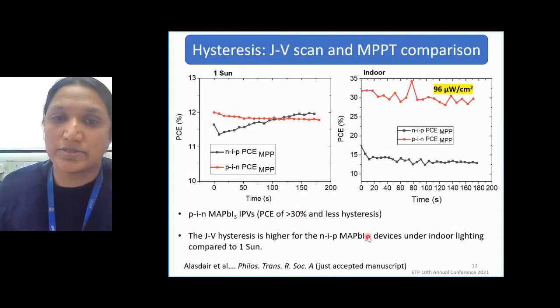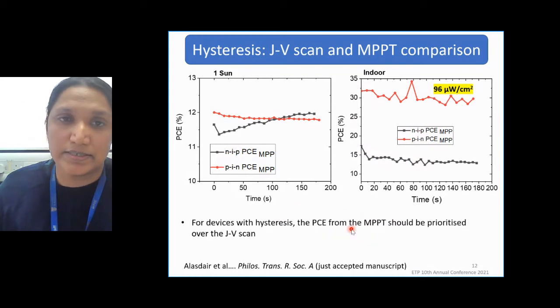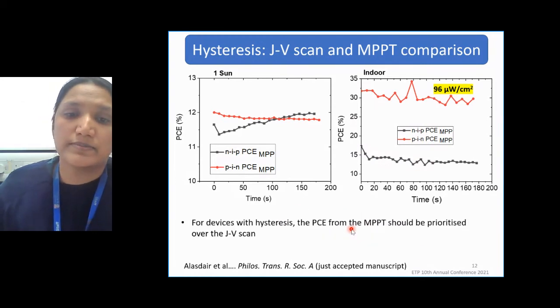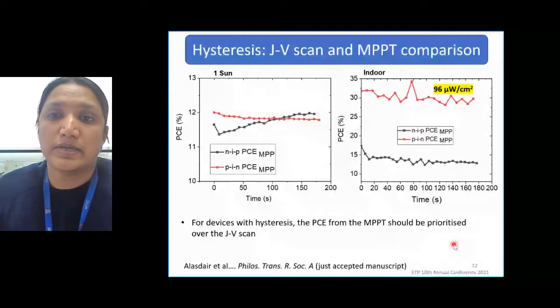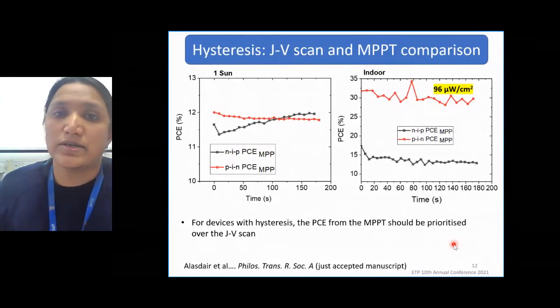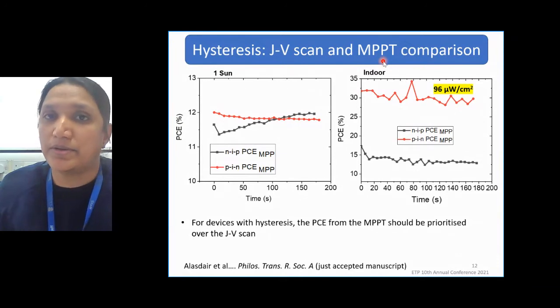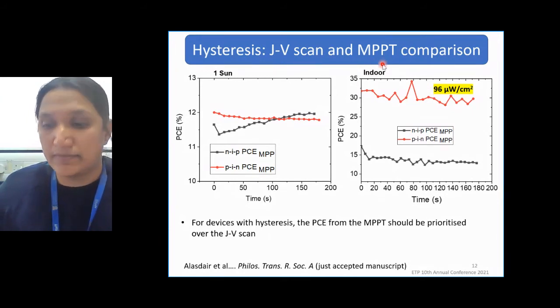Whereas in the case of NIP devices, they suffer from high hysteresis effect and it gets enhanced under indoor lighting conditions. So from the study, we observed that under indoor lighting conditions, especially for devices with the hysteresis effect, the power conversion efficiency estimated from the maximum power point tracking method should always be prioritized over their JV scan measurement, because the JV scan measurements will not give you reliable efficiency values when the devices have hysteresis effect.